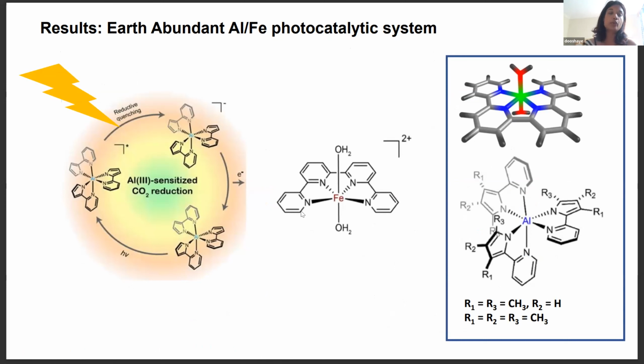So for the first time, we employed aluminum-based photosensitizers, which upon photoexcitation form a ligand-centered charge transfer state. We coupled it with an iron catalyst that was functional for both CO2 reduction and proton reduction.